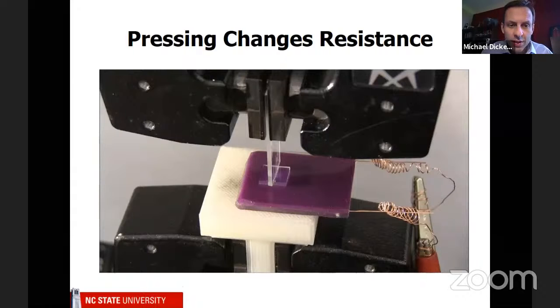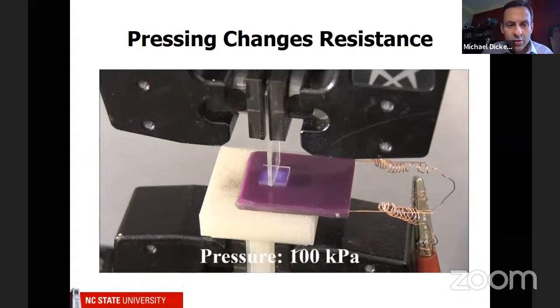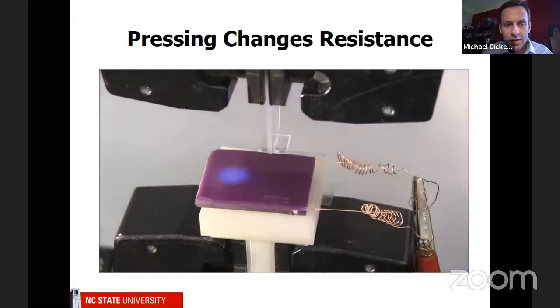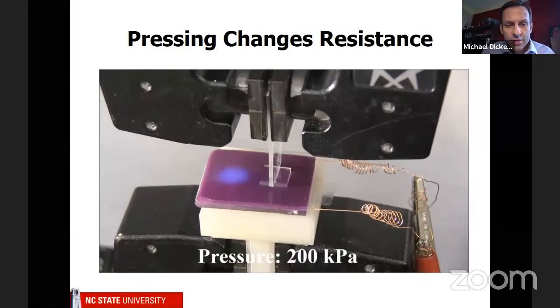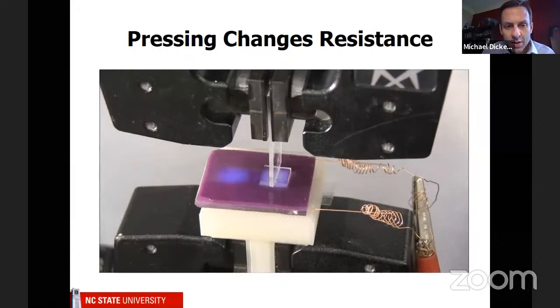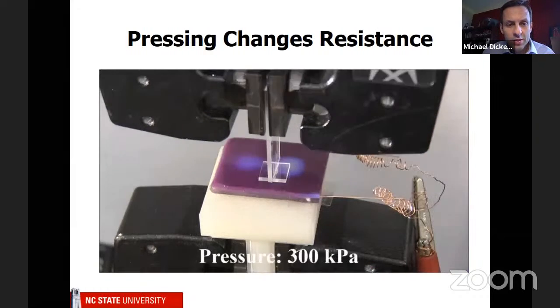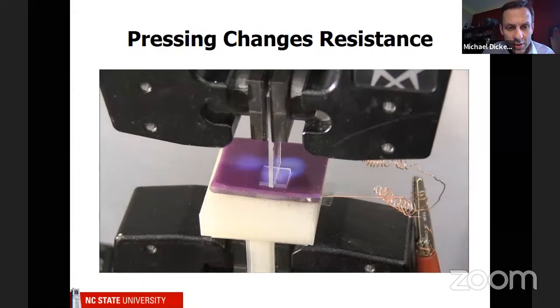When we do that, we increase the resistance right here. So when you apply a little bit of pressure, you can start seeing color change. So now we apply more pressure and we see more color change and more pressure. Okay, so now we have a way to make this material responsive to touch. But it actually is a little bit even more interesting.